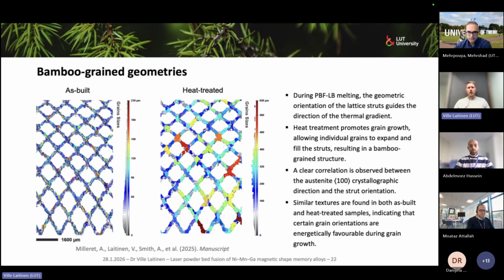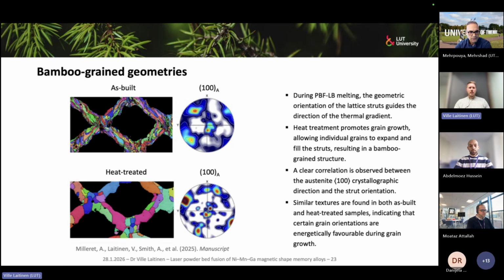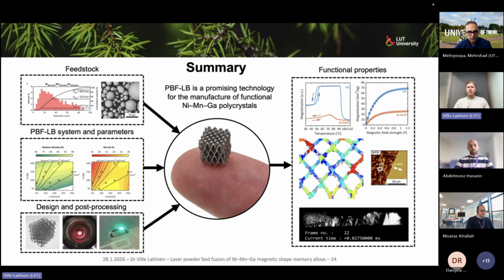The nice part is also that this crystal orientation tends to follow, because of the thermal gradient, the actual strut direction, and because of this we have crystallographic texture of austenite, which is then translated to martensite. Also after the heat treatment we don't lose this texture significantly, so we still maintain some primary directions, which of course should still be modeled a little bit better. So can we manipulate this behavior a little bit more? This is a short summary. We have lots of different considerations from the feedstock and processing point of view, and then what we can do with the functional material. Thank you.